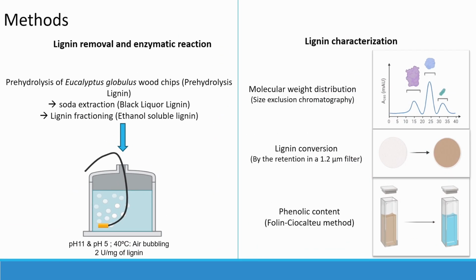This lignin can also be fractionated. Yes, we can also do a solvent fractionation of this lignin to achieve different groups of the raw material lignin. In this work, we also studied 2 different LACCASEs, one with better reaction at high pH, and one at pH 5, so that we can compare the results.